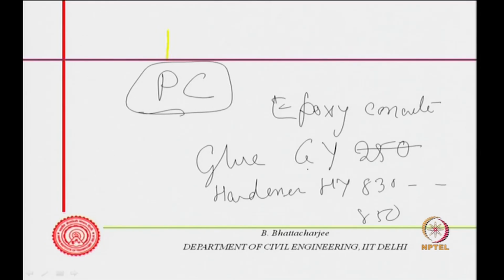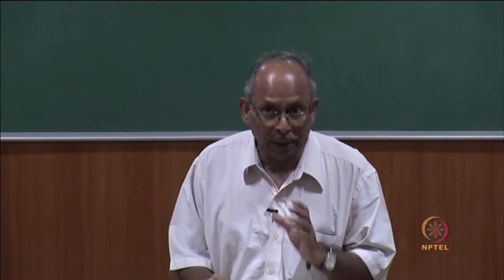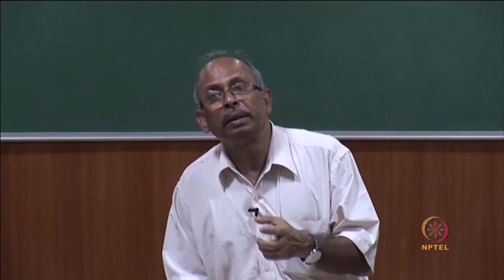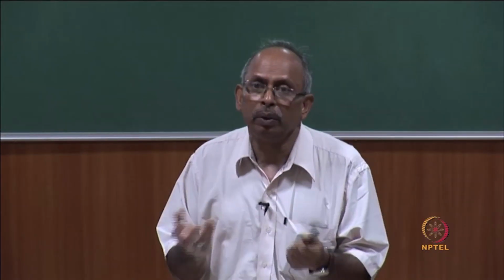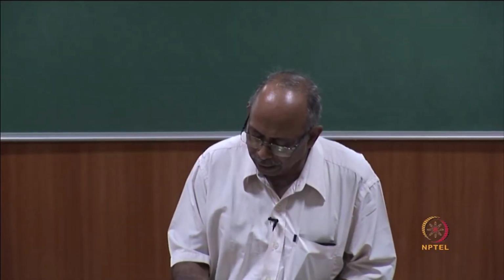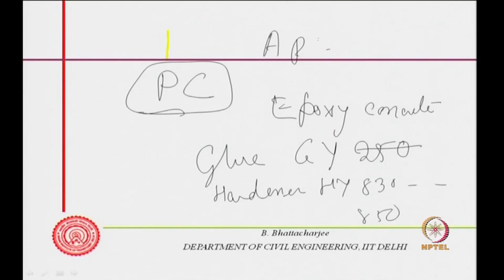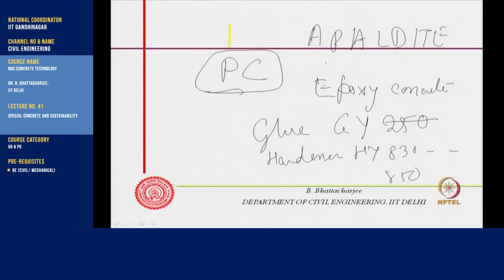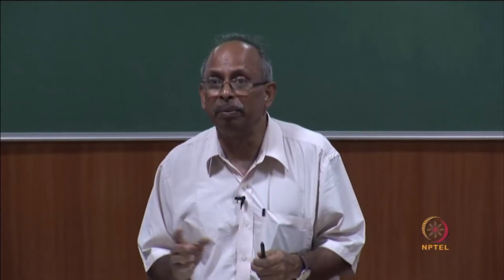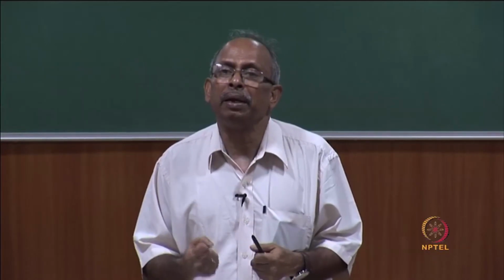So, you mix the monomer or resin with the hardener system and put sand into it. Now, just a simple example, you can take the example of araldite. It has got a glue and a hardener. Now, you put some sand together in this araldite, it makes you an epoxy mortar. But the difficulty is that the mixing process, the viscosity of the system, the stickiness of the system is such that it is not easy to make them. So, you have to have special kind of ones.